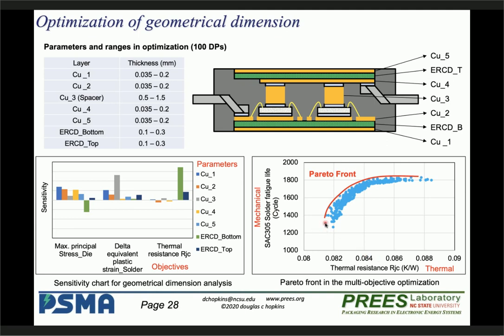So, for example, if I need the fatigue life higher than 1800 cycles, it's over here. That means my optimal thermal resistance is around 0.084 degrees per watt. Because our target is going toward the top left side, higher fatigue life and lower thermal resistance. So our target is in this area.